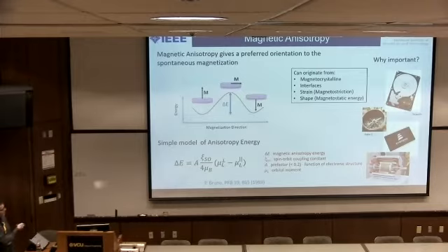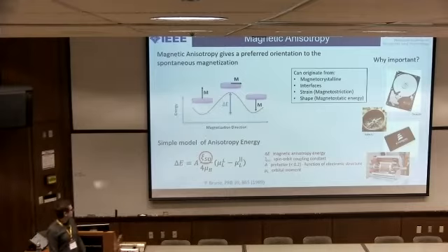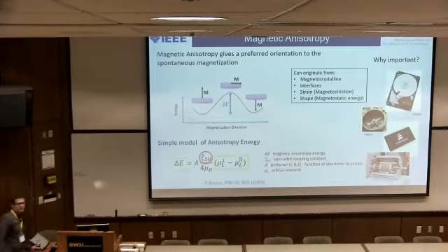Here we have the anisotropy energy, and it's proportional to the difference in the orbital moment along, in this case, the perpendicular case, the easy axis, and the hard direction, or the in-plane axis. So the difference in the orbital moments between those two. And the proportionality constant between those, of course, is our friend, the spin-orbit interaction, shown there. Now, the nice thing about FMR is that we can measure both sides of this equation simultaneously.